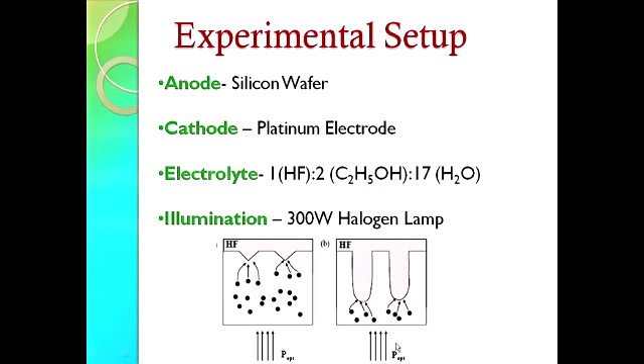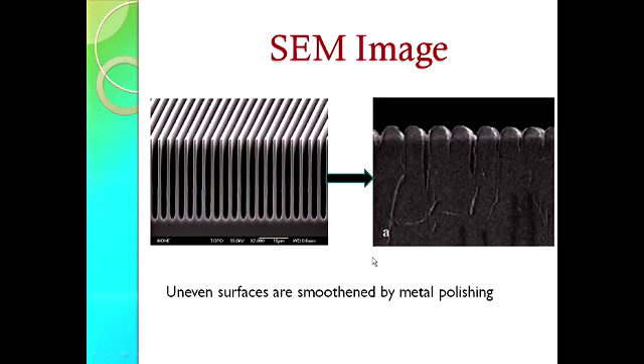So when the halogen lamp was switched on, there was photonic absorption here, and there was generation of holes which reacted at the V grooves, and that's why we had the V grooves etched previously. So the trenches were formed by dissolution of silicon, and this is how it looked after the formation of silicon pillars, and this is how it looks after oxidation process. Here we can observe some uneven surfaces which can be overcome or smoothened by metal polishing.